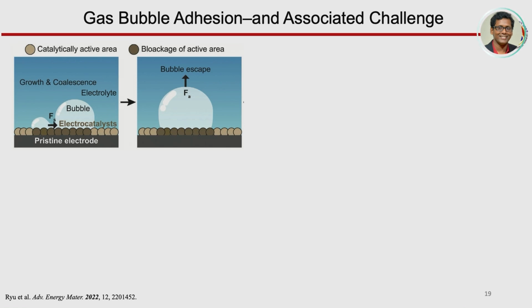So in this water splitting, the product is hydrogen, which is a gas. It has a natural affinity toward the solid surface, okay. And when that is there, it can block the electrode surface, this catalytic interface, and make it inert, because there is no contact between the electrolyte and the catalytic surface, unless this bubble is displaced from the electrode surface. Those who have performed this electrochemical HER have often seen hydrogen bubbles produced become bigger and bigger, and then they detach. I think many of us have also seen, when drinking carbonated fluids, if you shake it, you see the bubbles forming on the container, right, forming a bigger bubble and coming to the top, right.